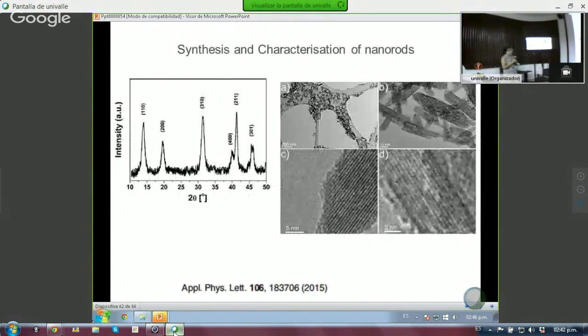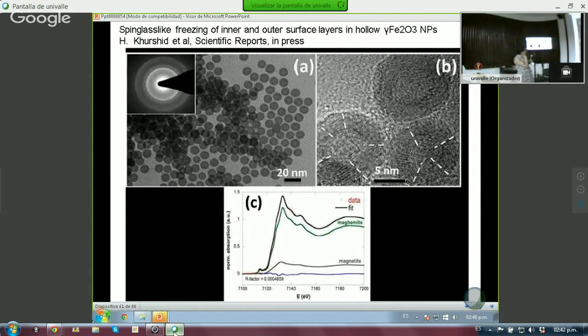On the same, yes, on the same particles. So, you know, you produce a batch of them, and these are the hollow rods, so the inside is empty, and then you take the same samples that you used and you run them at the APS, at the synchrotron, and you adjust the energy in a way that you're scanning across the K edge of iron. And then you record this, and it really takes 5 minutes to do it.